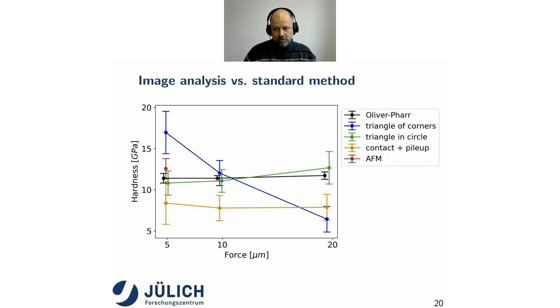And if we do that for the hardness, we see, as I told you before, we have these three ways of measuring the area. One is the triangle of corners, one is the triangle in the circle, and one is the contact in the pileup. And then we compare it to the traditional Oliver-Pharr method, right? So the traditional Oliver-Pharr method doesn't depend on the force. It has a rather low uncertainty, and so it's definitely right now the standard.